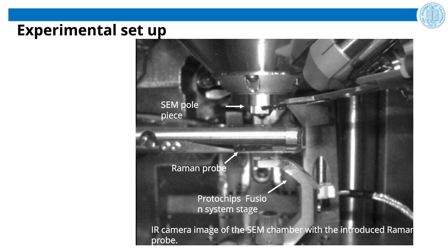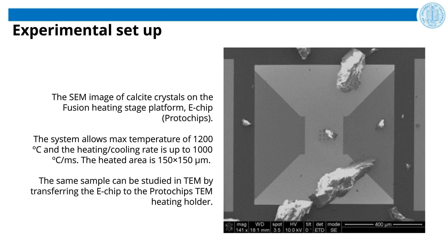Here we can see a secondary electron SEM image of the heating stage platform with the sample deposited. The heated area is approximately 150 by 150 micrometers, which is right in the middle of the E-chip.